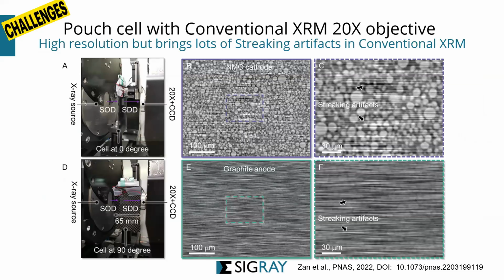But then when we want to do, let's say, in situ or in Operando on a real sample, like for instance, what if you want to study a pouch material or pouch cell? You find that if you run this under the conventional X-ray microscope mode, you will see what you call lots of streaking and lots of noise, like what we see here, using a traditional X-ray microscope with a 20x objective lens. And you see streaks, and with these streaks, it's impossible to do quantitative measurements of the size of the pores and to even identify where the locations or the defects are.